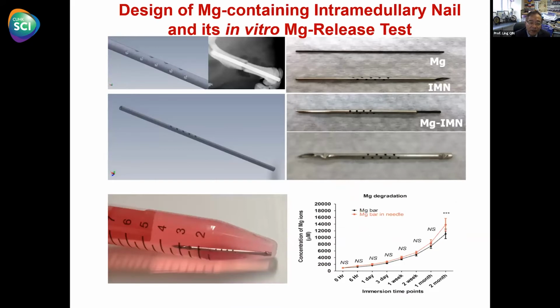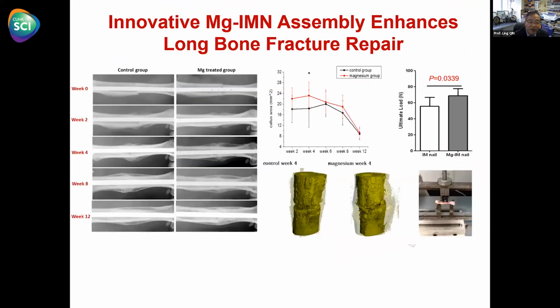This is the proof of concept study using a conventional intramedullary nail for fixation, where we incorporated the magnesium pin by drilling the hole so that it can degrade over time without sacrificing the mechanical strength of the fixation. And we demonstrated its gradual release.